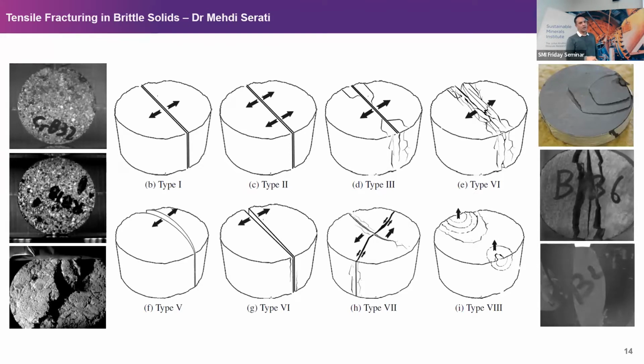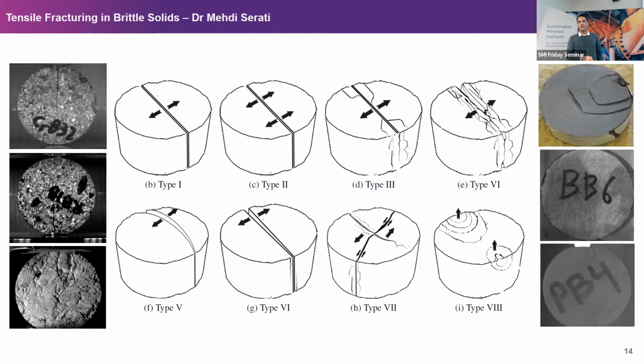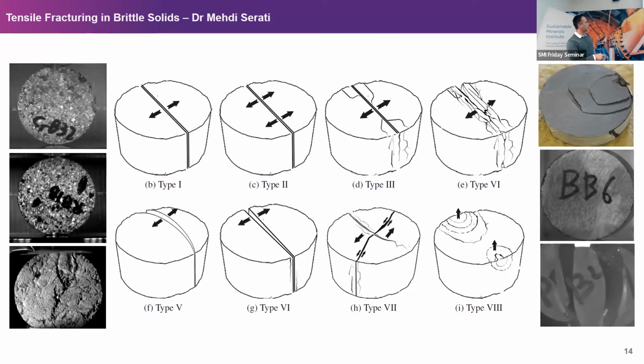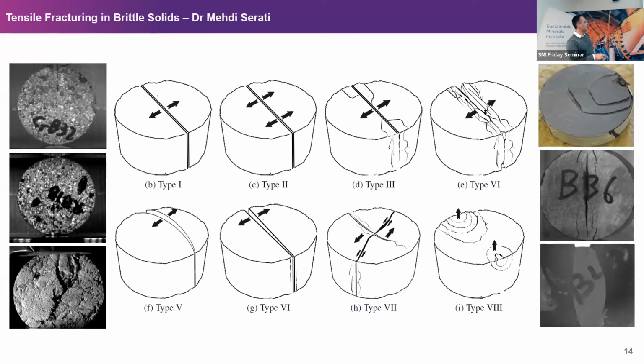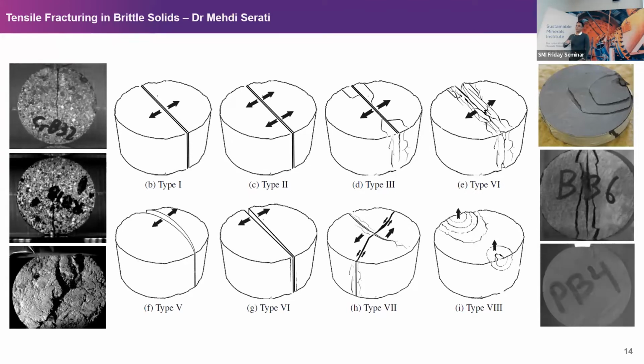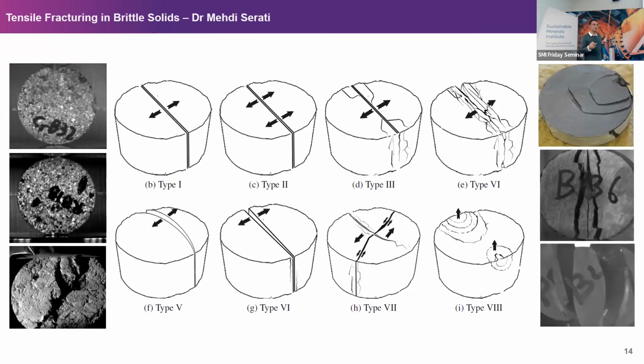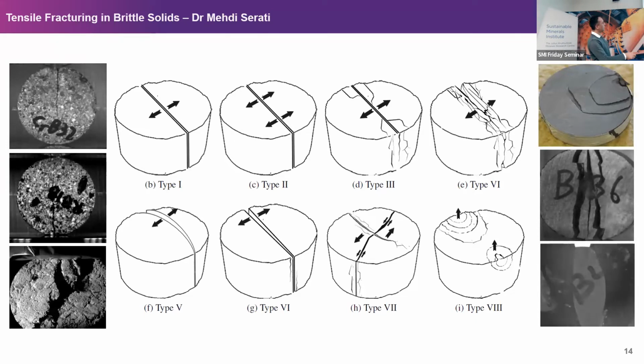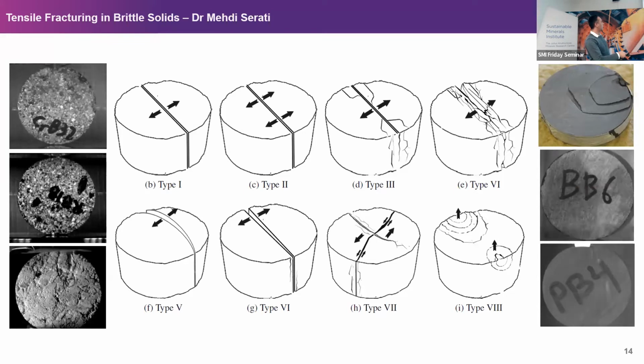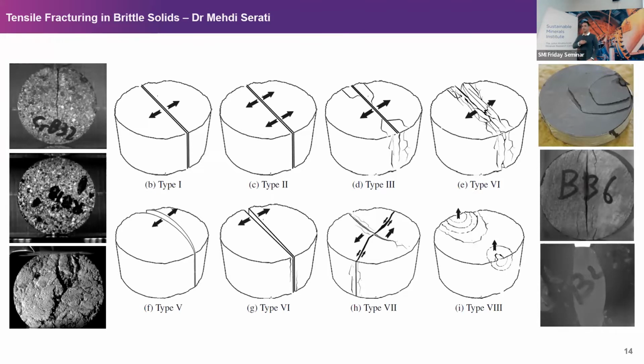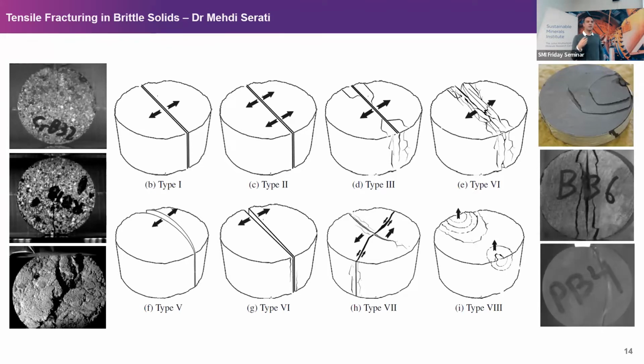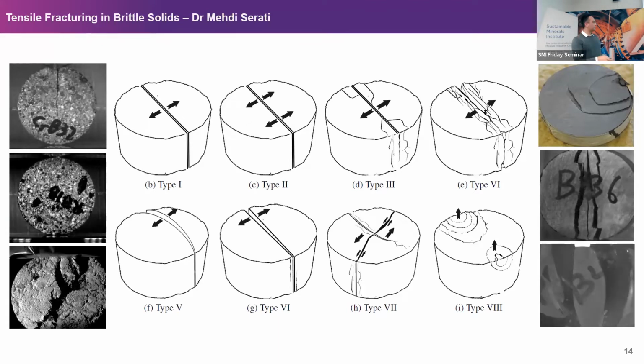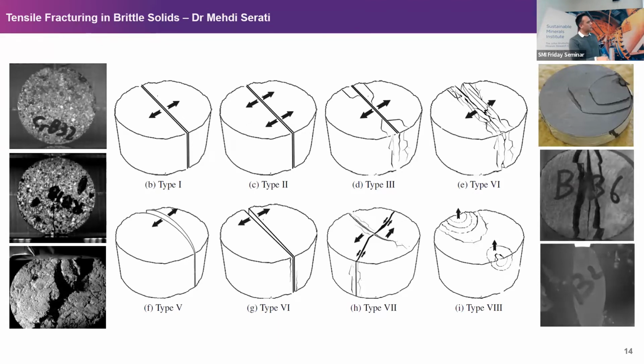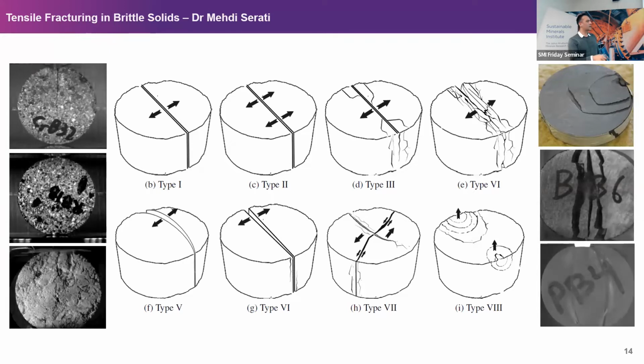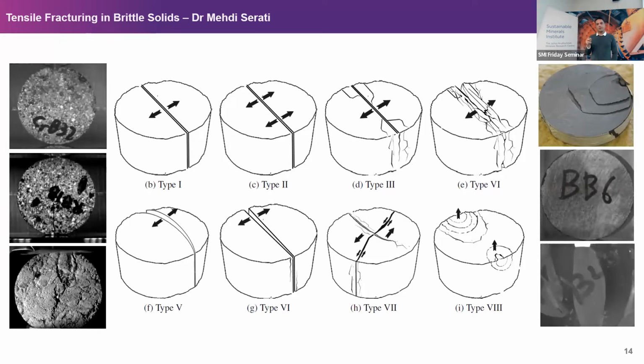This one is very interesting. We could observe it only in asphalt, and this is what you see here at the lower left corner of the screen. There was a transition from tensile to shear at some point during the crack propagation. As you can see here, and I'll try to illustrate it in this cartoon, you get the tensile crack at the center, and then it suddenly becomes a shear rupture, and we feel that it's related to the cementation and also the aggregate size. And the last one we only observed with graphite. By the way, in all these methods, we applied ISRM.